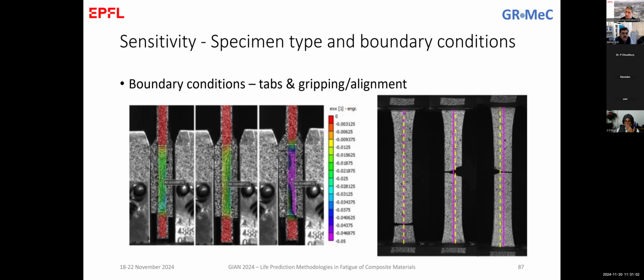load correctly. I will tell you what we did once. We were testing wooden specimens, this type of wooden specimens, typical dog bone specimens of wood. Okay, my drawing skills are not better than on Monday, but what we've seen is that we always had tab failures, and then we kind of invented methods. So the specimen size for us was not the specimen size defined by the standard, but we made the specimen like that, more or less. Yeah, non-standard samples.